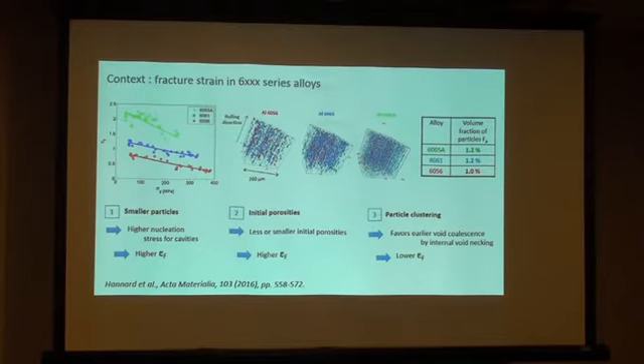Also, there is a huge effect of the initial porosities in these materials, and if you have smaller porosities, then you have higher ductility. And finally, there is the particle clustering. Of course, within a cluster, the particles are closer to each other, so this will speed up the coalescence process, and you will lower the ductility.